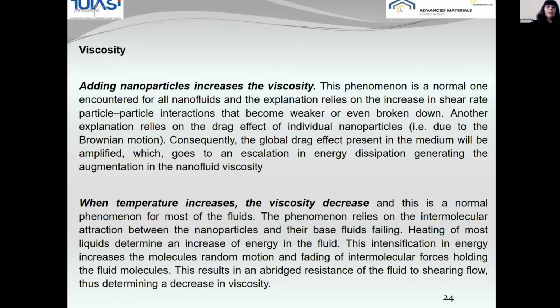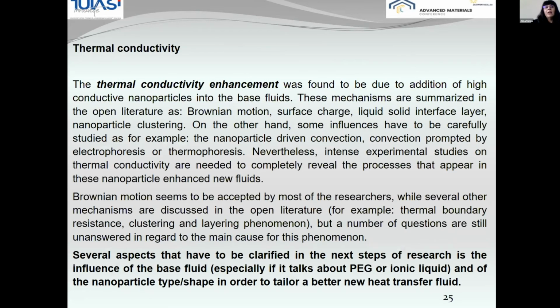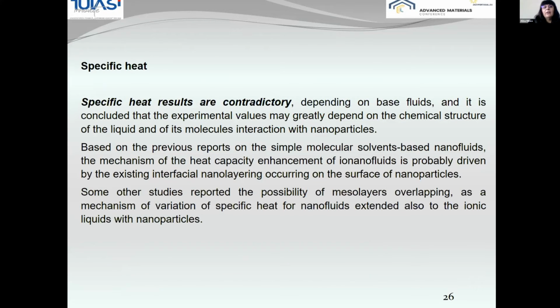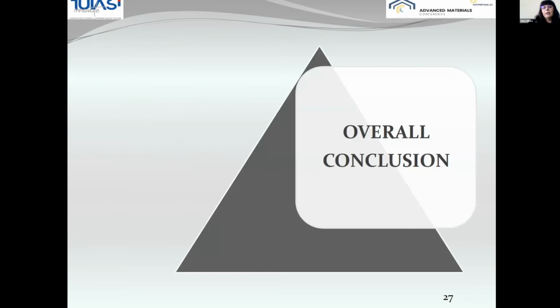So in general, the mechanisms that are guiding these nanofluids are in regard to viscosity. The addition of nanoparticles increases the viscosity, and when temperature increases, the viscosity decreases, as for most fluids. In regard to thermal conductivity, it is clear that the thermal conductivity enhancement is very high, and this is especially due to the addition of solid nanoparticles. In regard to specific heat, the results are contradictory and highly depend on the base fluid, and we have to rely on the experimental values.